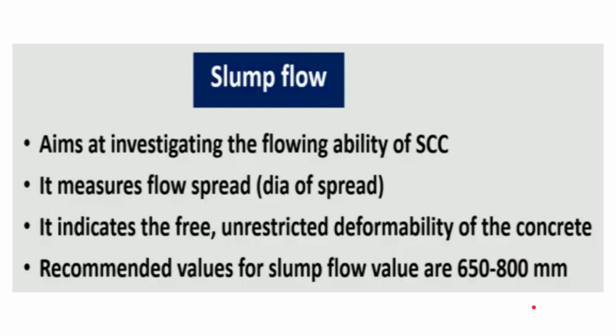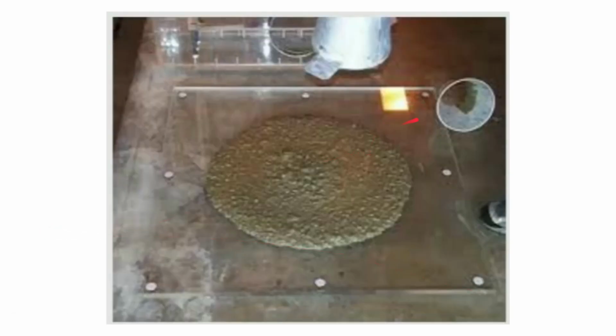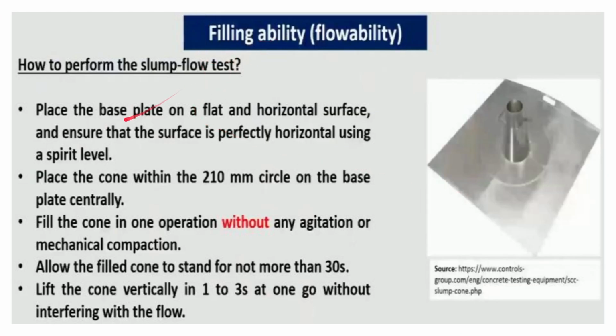Now as you can see here, this is a depiction of the slump flow test which has been carried out. Now we will see how it is done. So how to perform the slump flow test? Basically, we first place the base plate on a flat and horizontal surface, and ensure that the surface is perfectly horizontal using a spirit level. Then we place the cone centrally on the base plate, within the 210 mm circle.